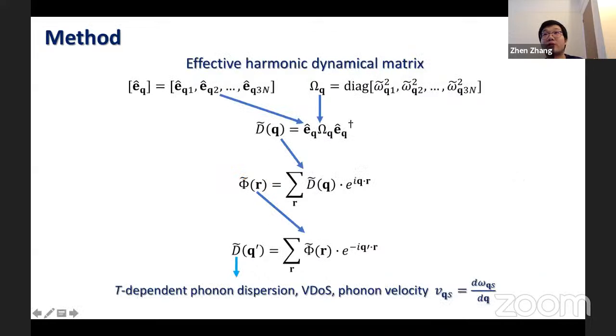After the renormalized frequencies are obtained, we next construct the effective harmonic dynamical matrix from the harmonic phonon polarization vectors and the renormalized frequencies. The effective harmonic dynamical matrix at any Q point in the Brillouin zone can be obtained by Fourier interpolation. By diagonalizing these effective harmonic dynamical matrices, the anharmonic phonon dispersions over the whole Brillouin zone, vibrational density of states, as well as phonon velocities can be obtained, all of which are temperature dependent.